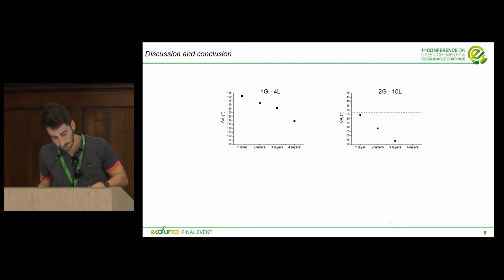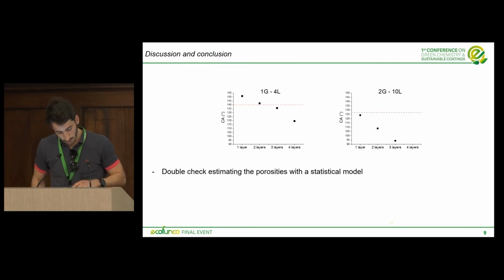On the other hand, for the first generation coating, the drop fell in the Cassie-Baxter regime in the second layer of the coating. And this is in line with what we have seen with the biological assessment, where for the second generation, the drop and the bacteria stop on the top of the layer, and for the first generation, the drop and the bacteria penetrate the coating. We also estimated the porosities and then the wettability with a statistical model, and not only with an imaging procedure that can be biased by the user.